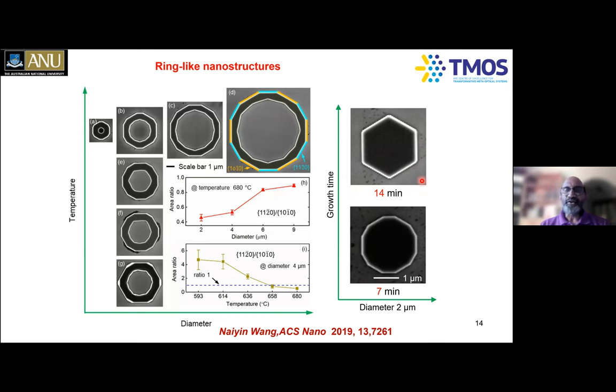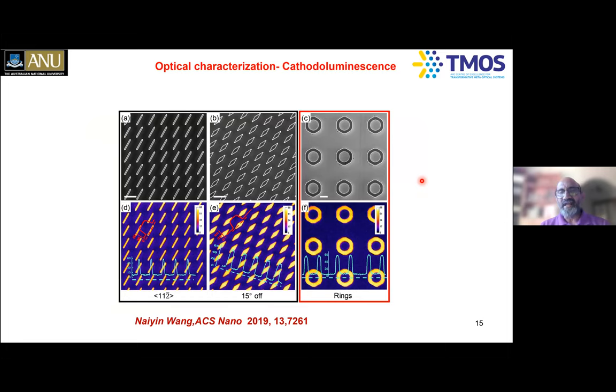So we've taken these nanostructures, the nanomembranes and nanodisks or nanorings, and then excited these with an electron beam in a scanning electron microscope, to really excite the electrons from the valence band to the conduction band, as and when they fall down and emit light. This is so-called cathodoluminescence. Earlier we were using lasers, that's why we called it photoluminescence. In this case, we are using an electron beam, so we call it cathodoluminescence.